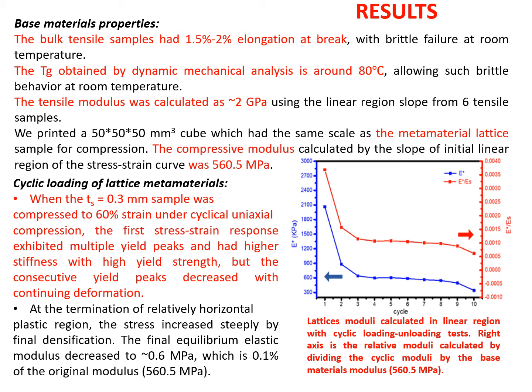We first measured the base material properties under tensile, DMA, and also compressive cases. The bulk tensile sample had 1.5% to 2% elongation at break. The Tg was around 80 degrees C. The tensile modulus was calculated as 2 gigapascal using the initial linear elastic region.